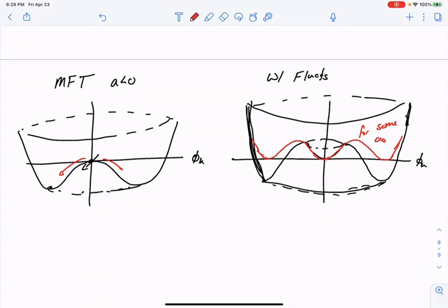Okay, so this is indeed what is found if you go in and try to measure experimentally something like a block copolymer undergoing its lamellar transition. One would observe a heat of that transition, the hallmark of a discontinuous transition experimentally, an abrupt change of the energy density releasing heat. There is no corresponding heat of a second order transition because there's no discontinuous change between phases.